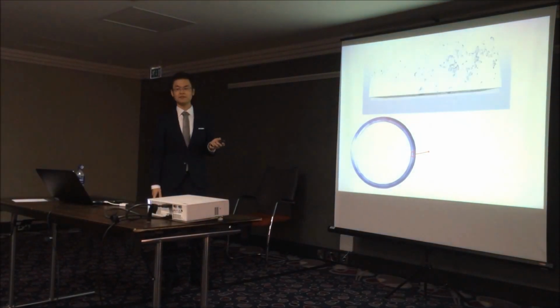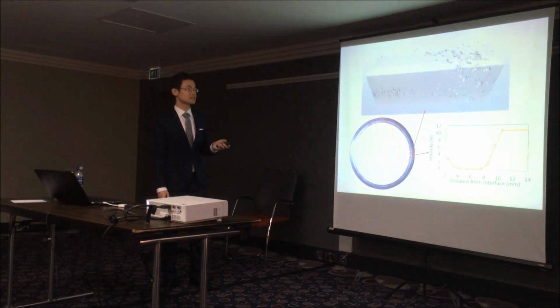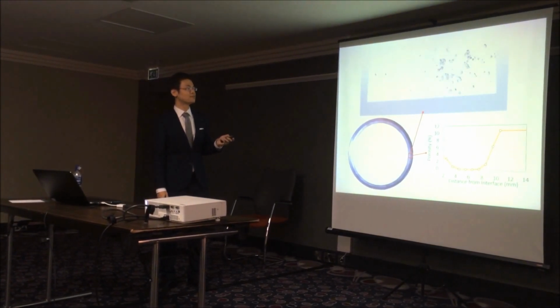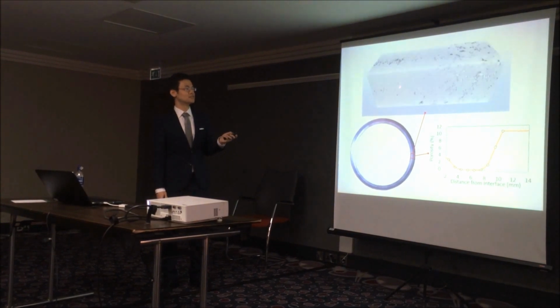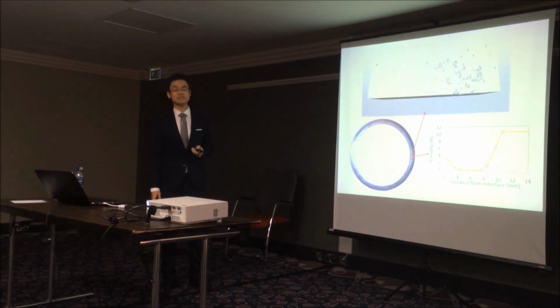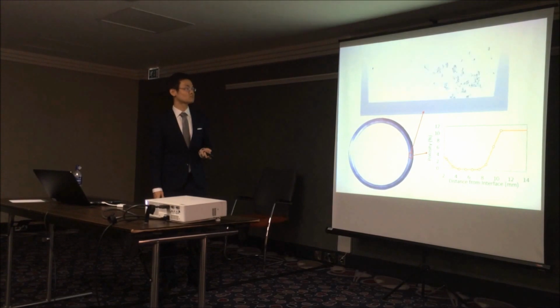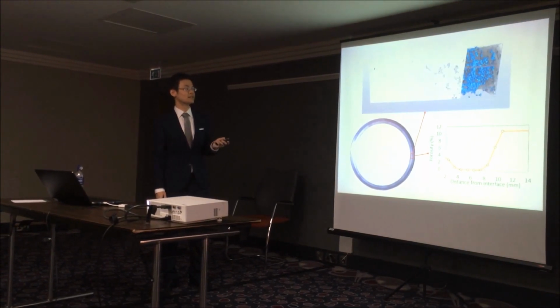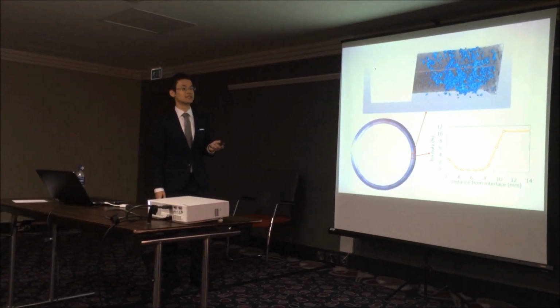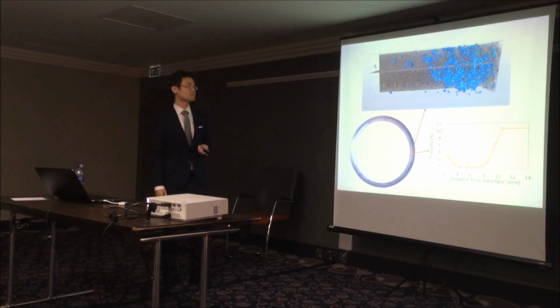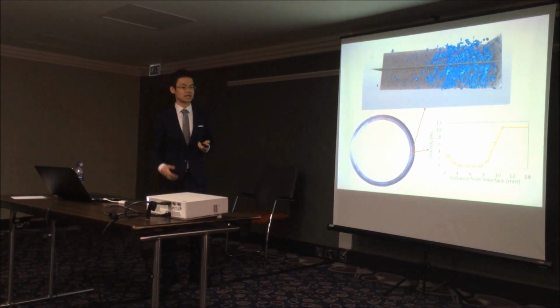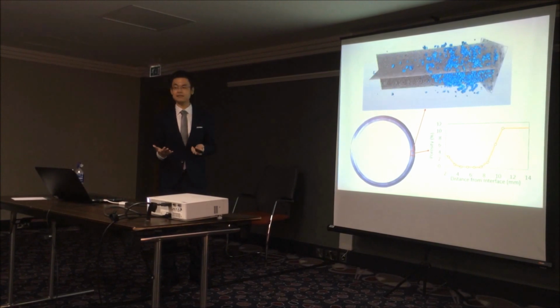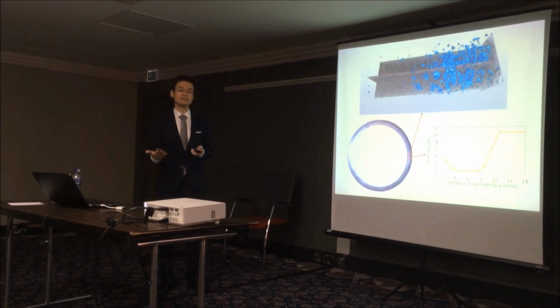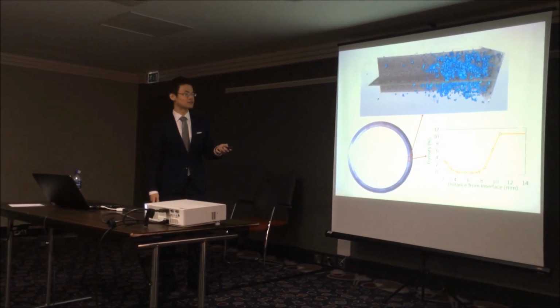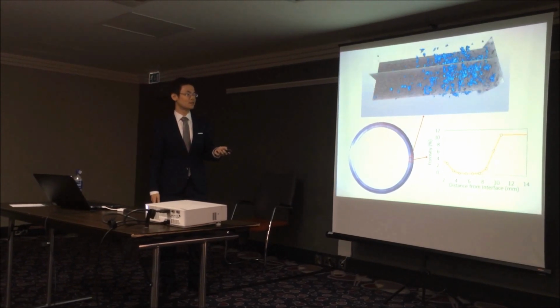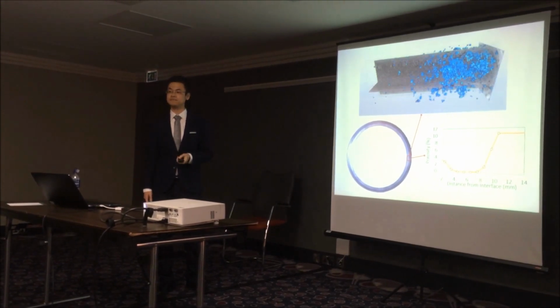So here we can see a 3D reconstruction of the sample surface. And we could roughly see the dense to porous transition region. Let's remove the sample surface so that we can have a clearer view of the porosity in the material. We can then quantify the porosity distribution in three-dimensional form. And therefore, for our sprayed steel, we have a step change of about 10% in porosity.